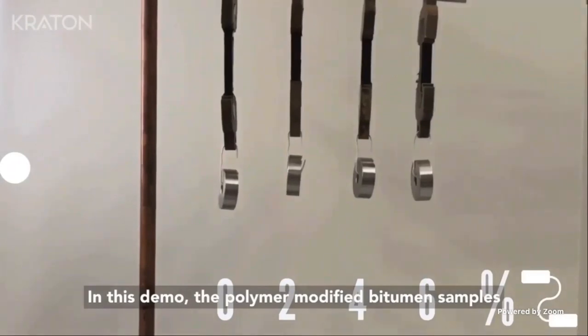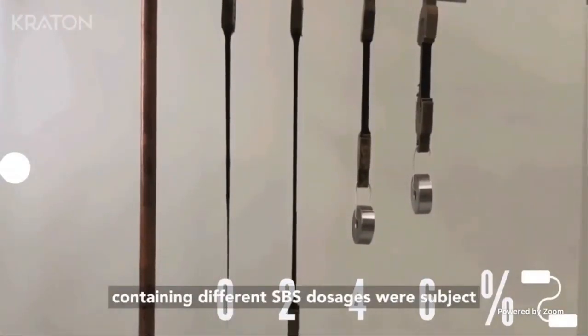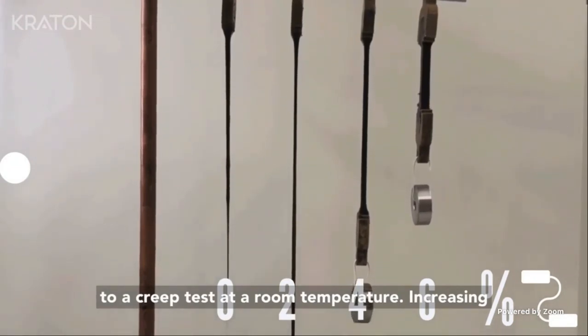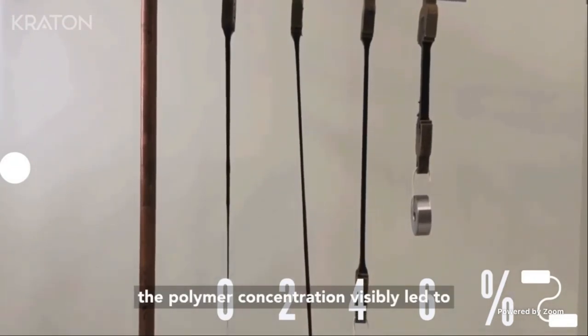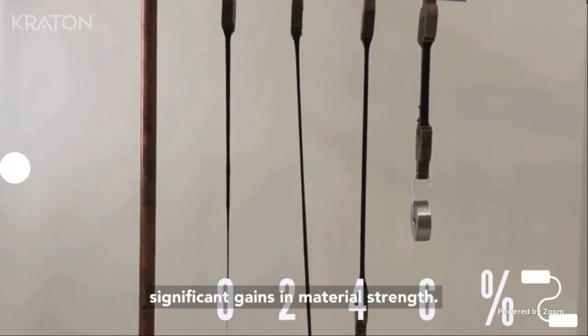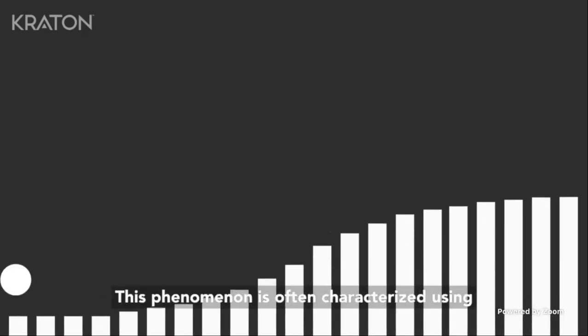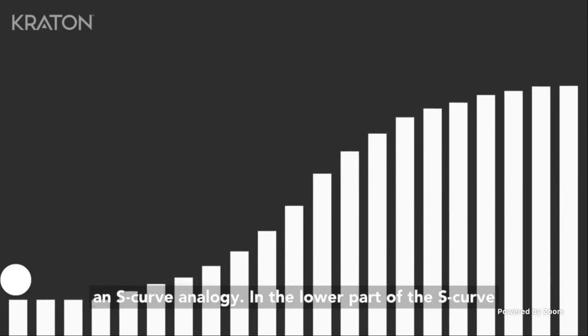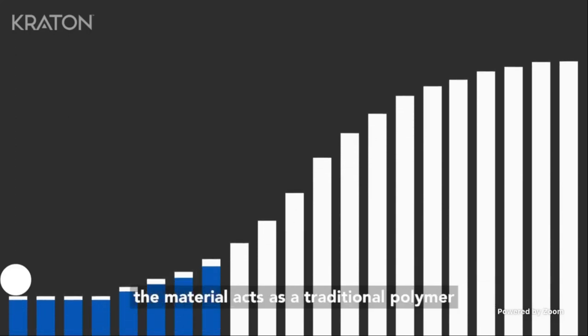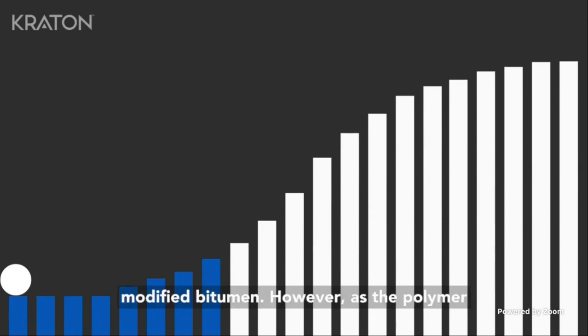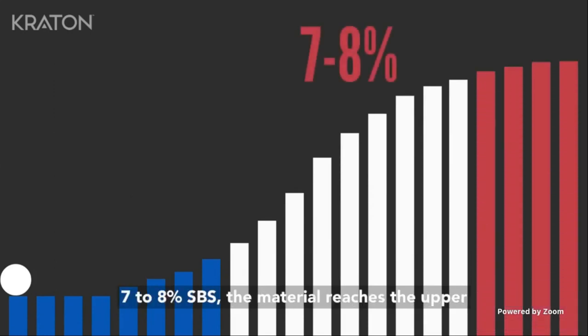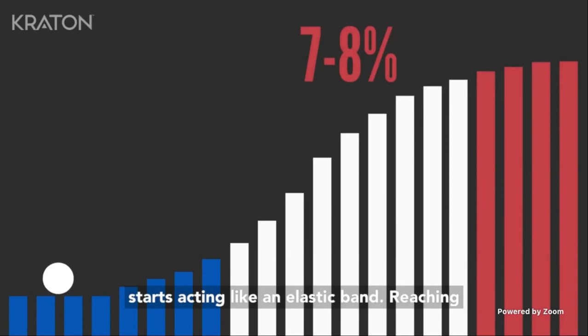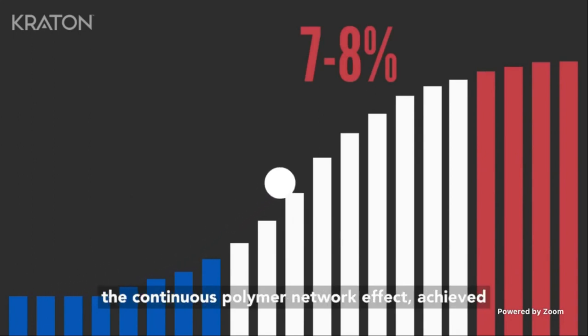In this demo, the polymer modified bitumen samples containing different SBS dosages were subjected to a creep test at room temperature. Increasing the polymer concentration visibly led to significant gains in the material strength. This phenomenon is often characterized using an S-curve analogy. In the lower part of the S-curve, the material acts as a traditional polymer modified bitumen. However, as the polymer concentration increases to approximately 7 to 8% SBS, the material reaches the upper plateau of the curve. In that region, the material starts acting like an elastic band, reaching the continuous polymer network effect.